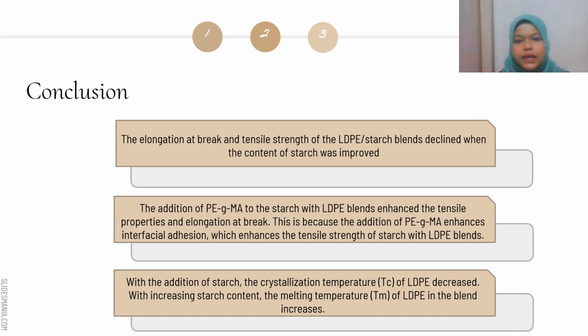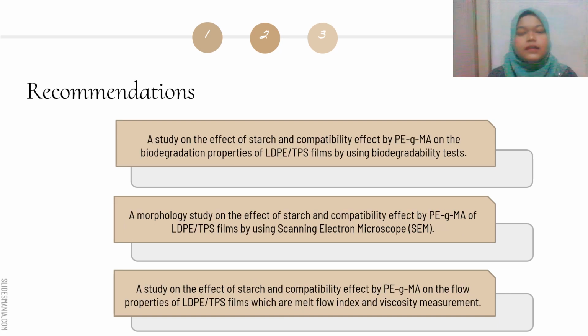The addition of PEGMA to the starch with LDPE blends enhanced the tensile properties and elongation at break. This is because the addition of PEGMA enhanced the interfacial adhesion, which enhanced the tensile strength of starch with LDPE blends. With increasing starch content, the melting temperature of LDPE in the blend increases. In general, the thermal stability is improved with the existence of starch. There are still gaps that can be filled in order to furnish more dependable and widely tolerable materials. All of these aspects should be given more thought and consideration in order to obtain better findings and results.